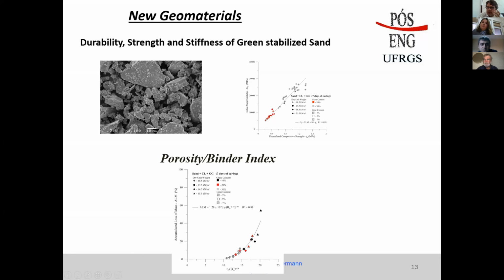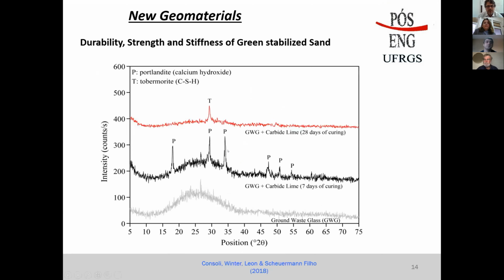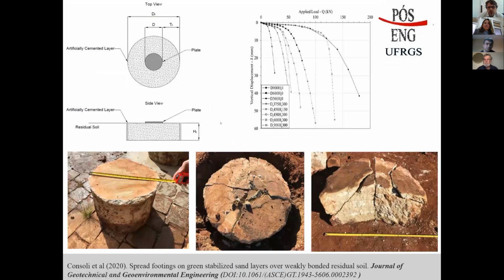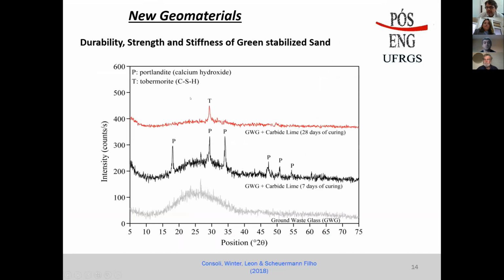And this curve, just to give an idea, shows that if you have one result, the curve shape is always the same. So you can have the whole result, which is interesting in order to reduce the amount of study that has to be carried out. Here are also some diffractometry studies showing that after some time you have produced tobermorite, which is the same thing that you produce if you have Portland cement. You have CSH in this case, which is tobermorite here, after some curing period.